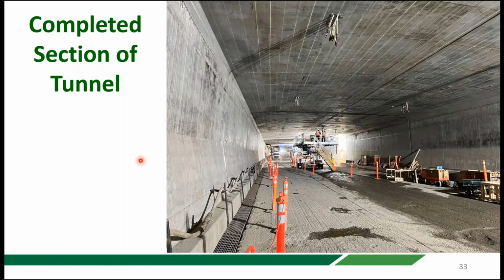And here you can see a completed section of the tunnel. All of the concrete work for the walls and the ceiling is done. You have a new concrete surface for the walls and a new concrete surface for the ceiling. And as with the two previous examples, the galvanic anodes are buried in this new concrete wall and underneath in the roof. And the purpose of those anodes is to protect the steel that remains in the salt contaminated concrete that is remaining there, to keep that from corroding for the design service life.